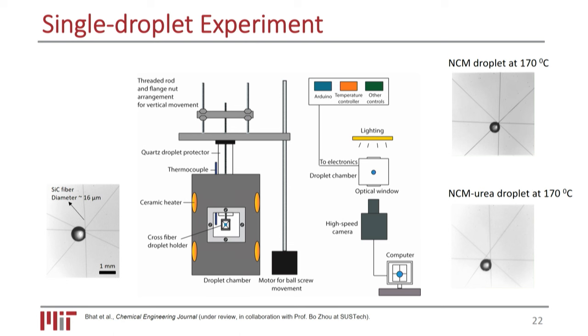And here is what it looks like. Please take a look at the upper right figure. It's very fast, and we do see that the particle shrinks, and by careful design, the droplet remains in its spherical shape, making it easier for us to do the further modeling by using this one-dimensional assumption because it's symmetric. There is nothing really standing out. It's just the diameter shrinks. And finally, it stops there because this is not a pure droplet, but has some solute in it, right? So the particle gets formed, and we have a solid shell preventing the diameter from being further reduced. And please take a close look at the video below. It's going to look different.